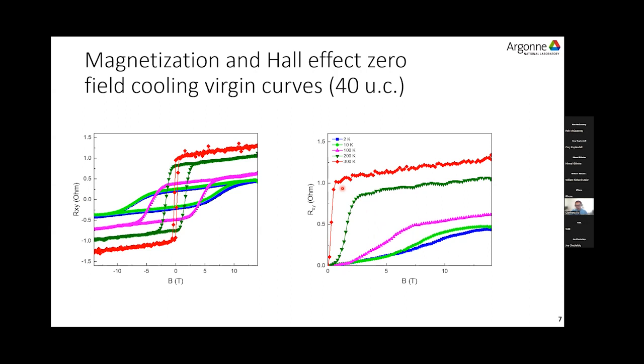The Hall effect could show the possible magnetic order of the manganese lattice, as in the terbium manganese six tin six thin film. The kagome lattice is formed by manganese atoms only. So the feature in the virgin Hall curves may come from several possible reasons, like a different magnetic structure, maybe a possible antiferromagnetic order in the manganese lattice, or a domain effect because of the island structure of the film, or maybe the manganese moments just fall into the hexagonal plane, which is different from the C-axis.